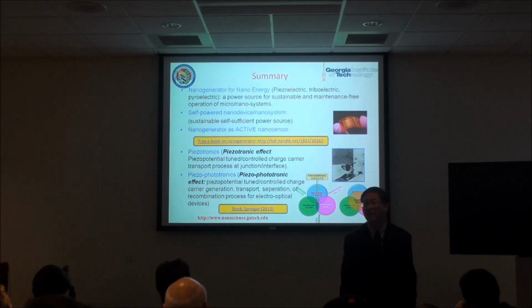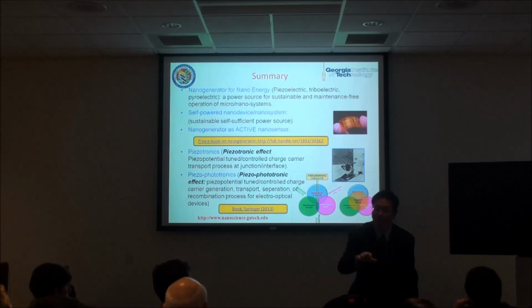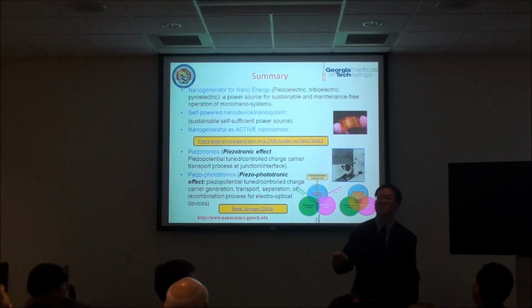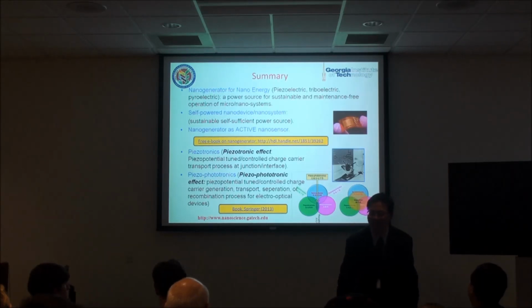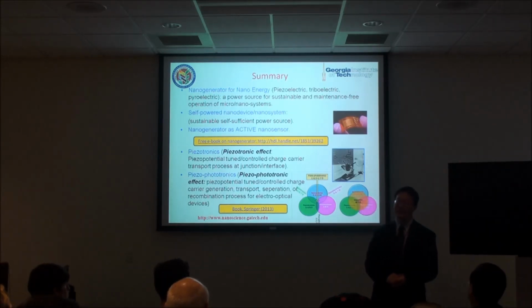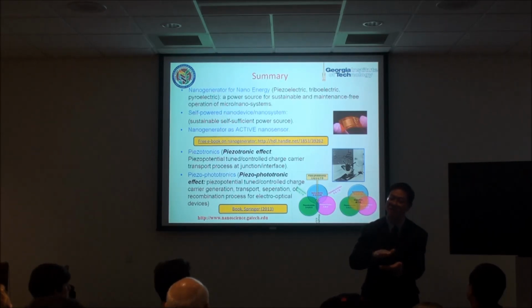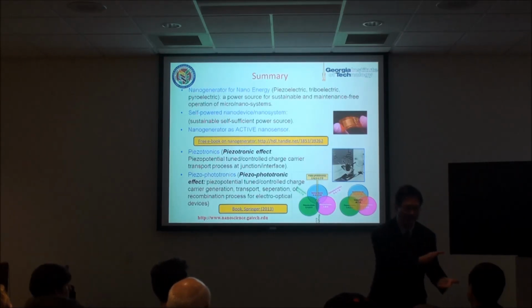So we consider it easy. Zinc oxide is very easy to fabricate: 85 degrees C chemical synthesis, which Zhong is the expert on. And it is environmentally green and biologically compatible. So that's why we choose it. There could be other materials better than that one, but in order to systematically compare, you have to have the same size and same density, then you can make a conclusion. Just saying, oh, make a PZT, this one is better than the other, is not very convincing. To make a good conclusion, we have to do that systematically.